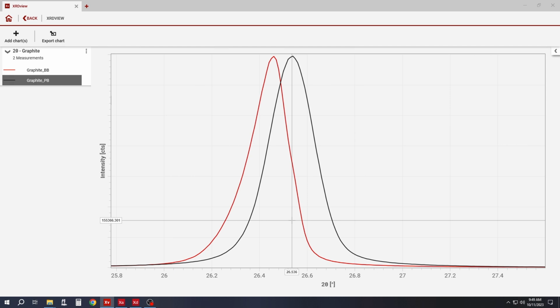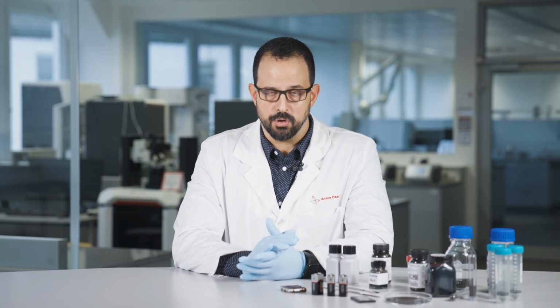Here, the peak position in the black curve, which is measured with parallel beam, is the correct 2 theta. However, the peak position in the red curve, measured with Bragg-Brentano geometry, is slightly shifted. And such shifts can be corrected by spiking the sample with a reference material with known peak positions. So, measuring the degree of crystallinity and degree of graphitization of electrode materials is a necessary step in the early stages of electrode manufacturing.